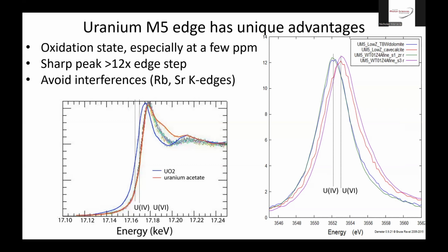So uranium is a good example of something with both hard X-ray and tender energy edges. So typically, uranium is looked at the L3 edge, which is shown on the left, and it shows a slight separation with oxidation state from 4 to 6.